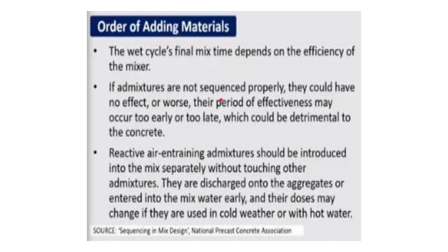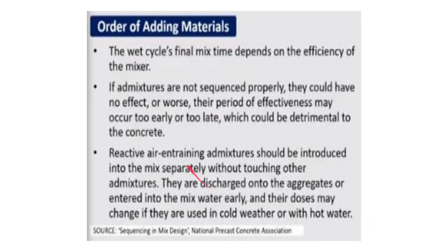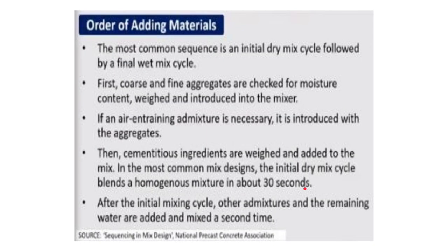If admixtures are not sequenced properly, they could have no effect, or worse, their period of effectiveness may occur too early or too late, which could be detrimental to the concrete. So the adding sequence is very much important in case of admixtures. Reactive air entraining admixtures should be introduced into the mix separately, without touching other admixtures.